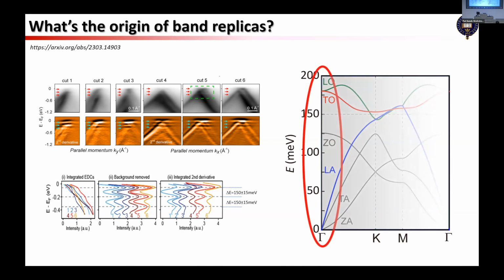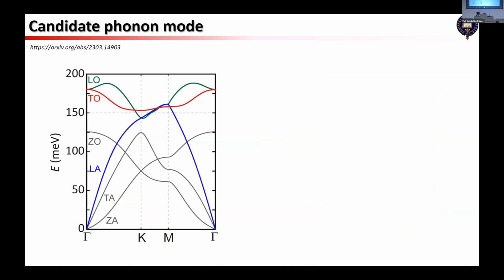So here, right, then there's nothing here. But then later on, we realized that in the MATBG system, this kind of zero energy momentum transfer doesn't necessarily need a gamma phonon. A K phonon can also do. So if we went to the K point vicinity, indeed there are actually three phonon bands going across it. And although we like this TO phonon, it's kind of flat, but we don't know yet.